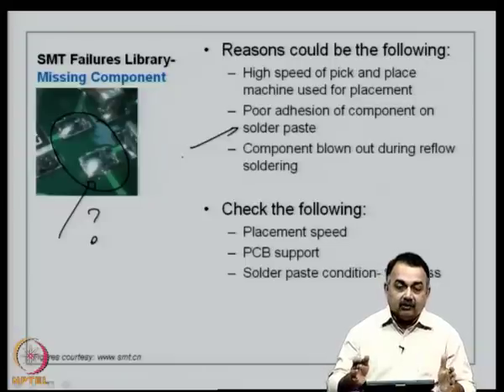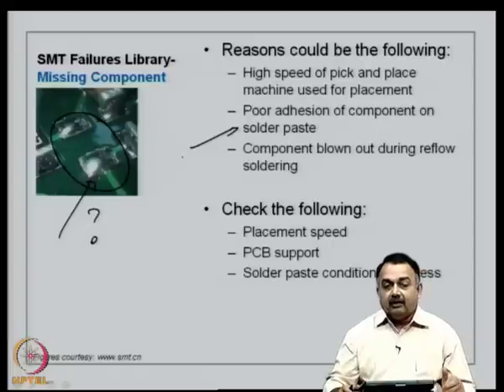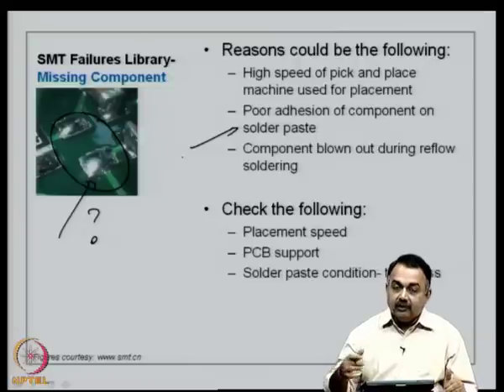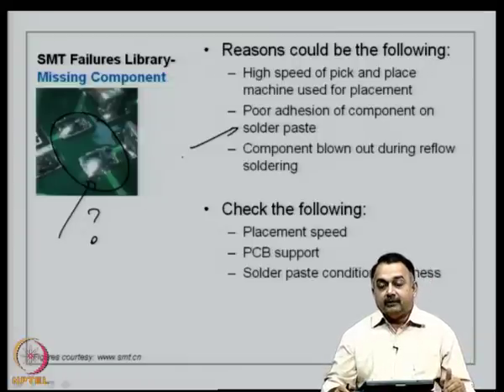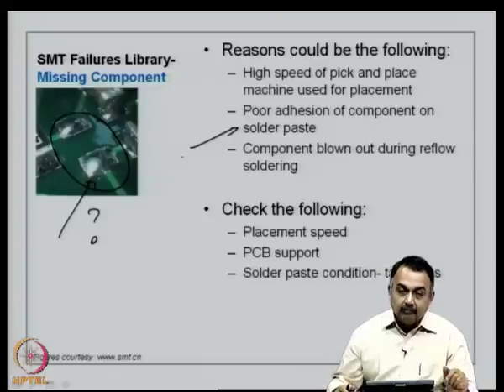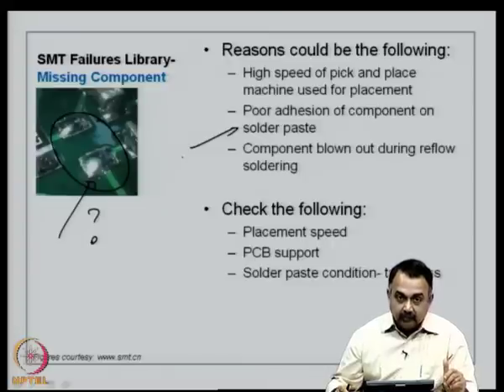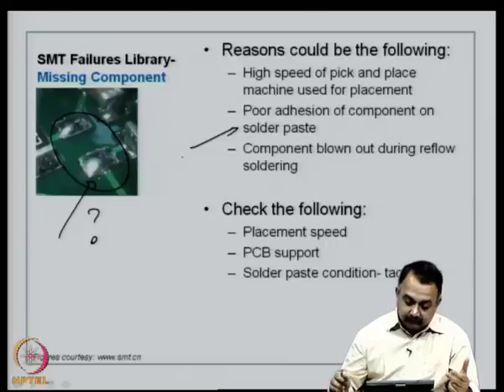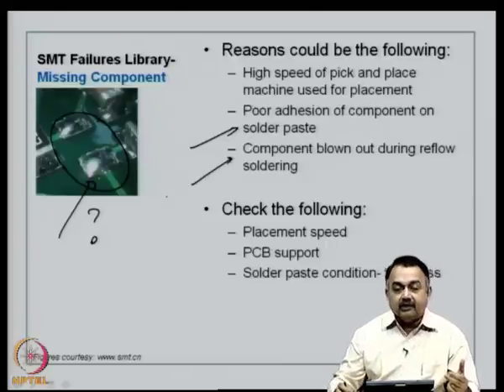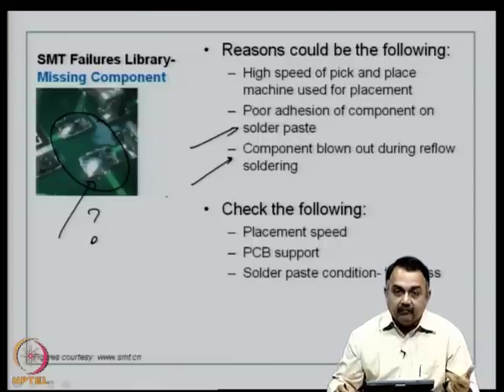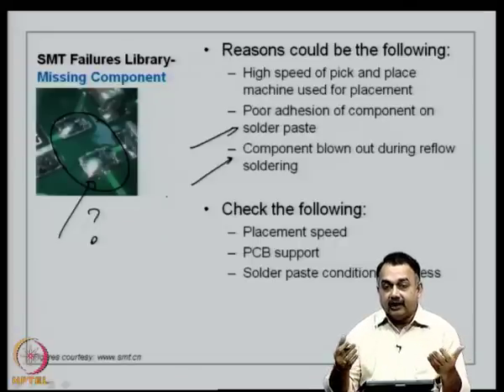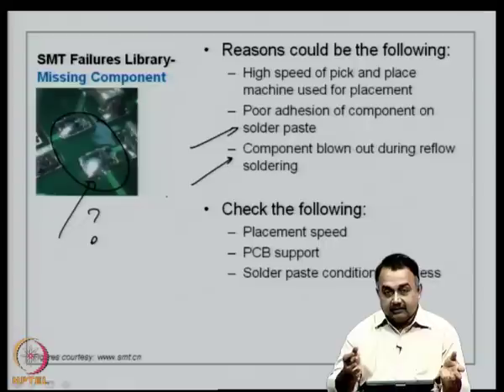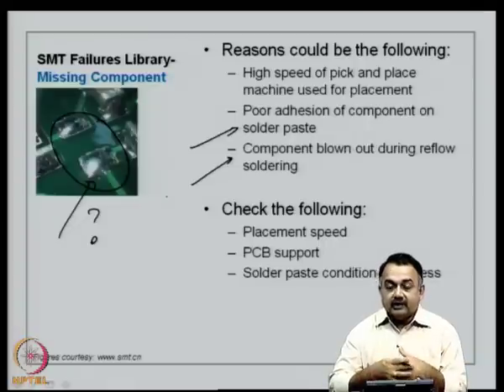In between there is a tacky cure process, that is you can do it at room temperature or at very low temperatures in the oven, you can do a tacky cure. But then before it goes for a reflow processing, the component should not move. So, misalignment of component could also happen when you consider these kind of problems with solder paste material. The other thing is when you work with automated machines, the component could have been blown out during the reflow soldering. Again, in a reflow, if there is a convection air, the component is probably displaced because of the air inside the reflow machine.